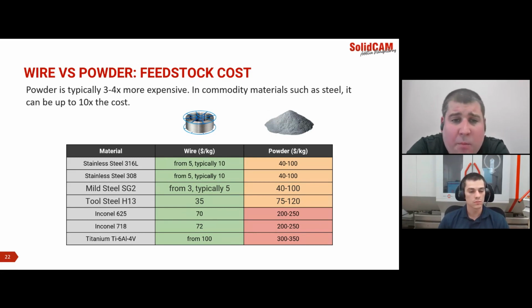Overall cost as well between wire and powder. In some cases, it can be 10 to 1. But the big takeaway is that we're using all of this feedstock, where with most blown powder directed energy deposition systems, you're really using anywhere from best case scenario around 70% feedstock all the way down to as low as 40. So even though in some cases we could be 10 to 1, the cost is actually even more significant than that. Could be 20 to 1 because we're actually using all of this feedstock versus a 50% utilization rate.